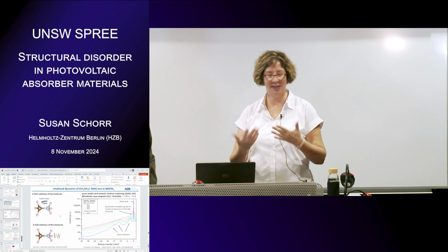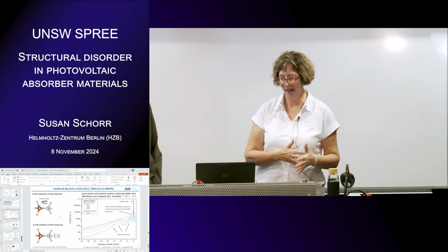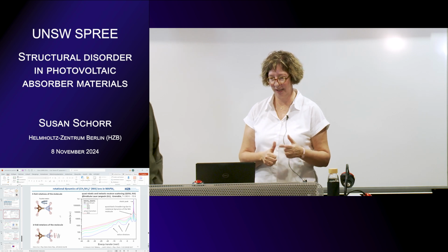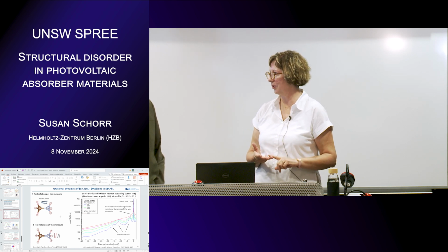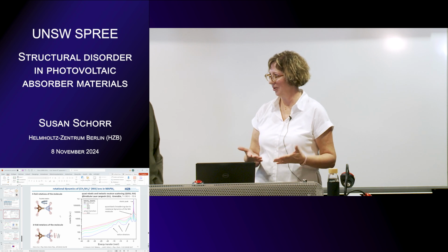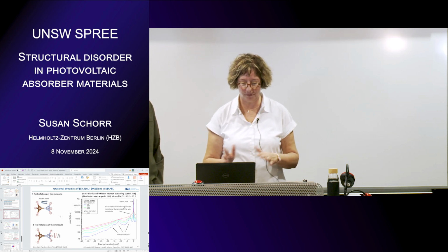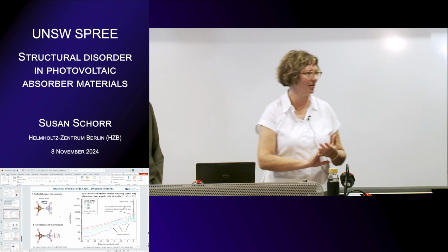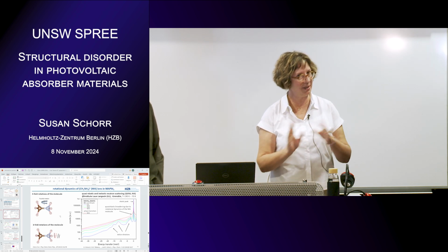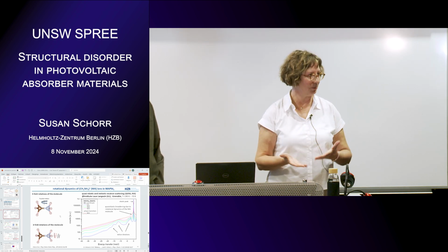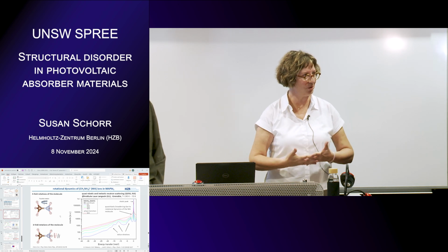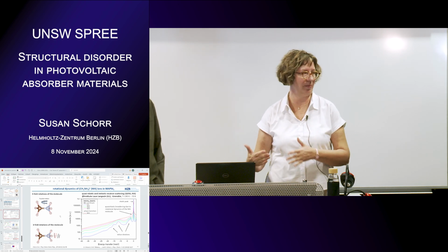And this was the idea from Alain Lafond. That's why it works for kesterite, for stannite, for Wurtz-kesterite, for Wurtz-stannite. We also measured the copper zinc silicon selenide, which is Wurtz-kesterite. It also shows the copper zinc disorder and the point defects. It's all the same behavior.